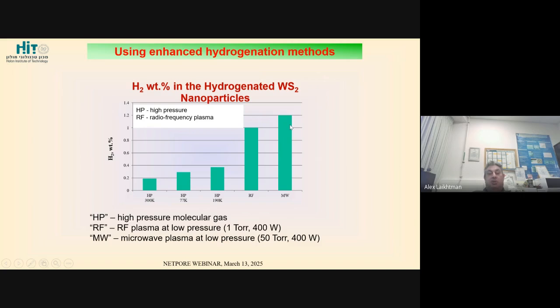The problem with microwave plasma, it was too aggressive. So sometimes there was a decomposition of the nanoparticles, and these people who performed plasma for us even could smell some H2S from the nanoparticles. They were not very happy about this. So we concentrated on RF plasma because it was stable, room temperature, no destruction of the nanoparticles, and so on, as I have just presented you in our previous applications.